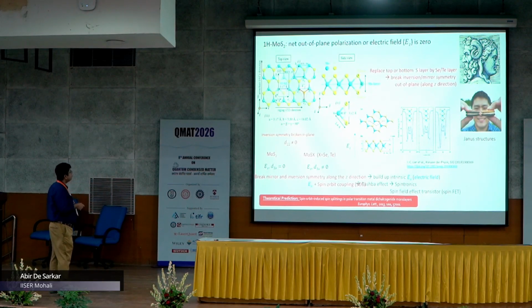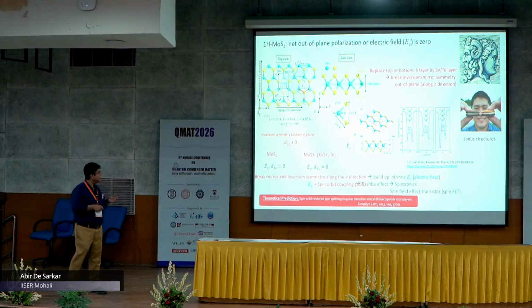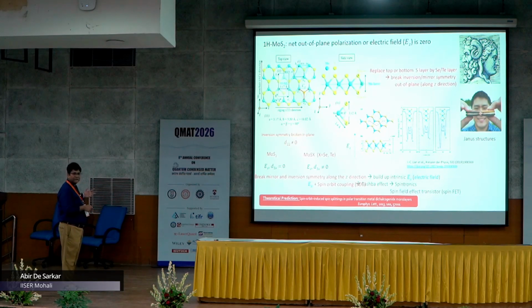And this is the top view of single layer MoS2, which shows that the inversion symmetry is broken in the xy plane of this monolayer, for which it shows in-plane piezoelectricity. But the inversion symmetry is preserved along the z direction, for which it doesn't show any out-of-plane piezoelectricity or out-of-plane electric field. So how can you induce an out-of-plane piezoelectricity in this single layer MoS2? It is possible if you turn this into the so-called Janus structure.